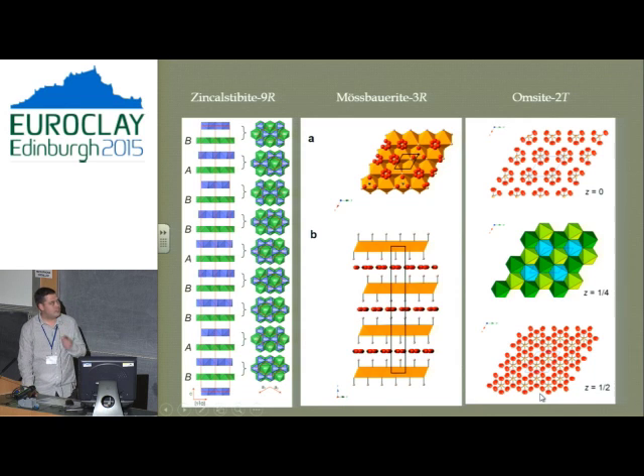So what do these structures look like? These are just some of the ones that we've done recently, at least in so far as we could find in the literature. We now have the record for the longest periodicity in an LDH mineral, and this is for zincalstibite. So we've got zinc and aluminium in the brucite layer, and we've got antimony octahedra in here. And the periodicity of this is about 89 angstroms. These are little crystals that we found in Italy.